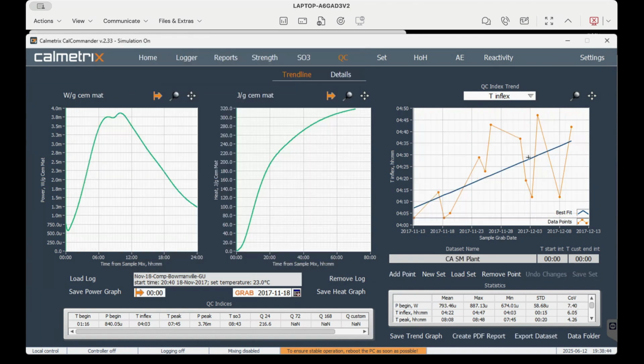So here, if I look here, for example, I look at the time of inflection. So what does it tell me? So it trends upward over time, but it goes up and down. It's kind of hard to assess whether that's a big deal or not. I have to look at the scale. I can say, okay, it's this time of inflection point, which is, as you remember, the point here somewhere where the reaction goes from accelerating to decelerating. That's sort of indicative of where my final set is close. And when I look at this, then I see it's somewhere between 4 hours and 4 hours and 45 minutes. So it's okay. It's within 45 minutes.